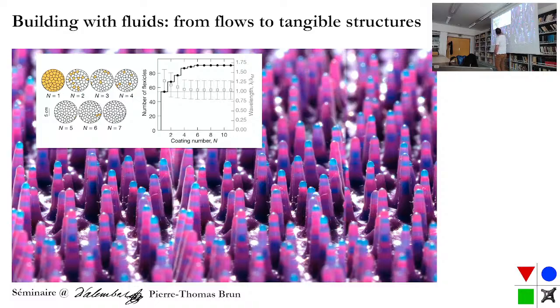And if you apply another coating, you see new drops appearing wherever there was too much space between already existing drops. And after 3 or 4 coatings, there are no more new drops that appear. And you're converging to something which is actually what is predicted by stability analysis. So you're quite far from linear problem, but the predictions actually work fairly well.